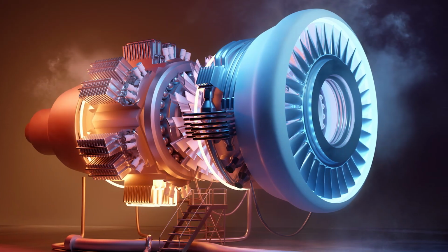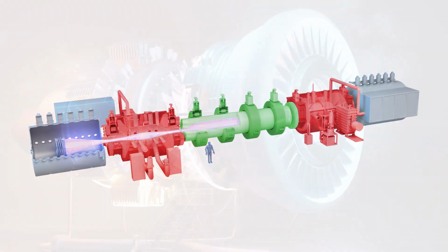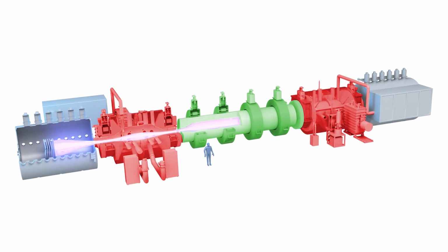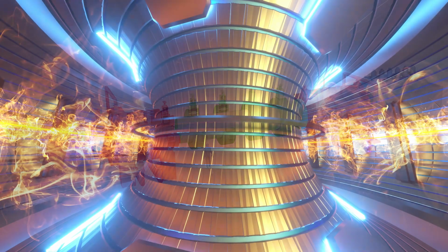We're looking at ways to make new alloys that are going to give us a boost in the energy economy. One way to do that is to go to higher operating temperatures. The jet engine will operate around 1100 degrees C. We're looking at going to 1300 degrees C, or for hypersonics, or for fusion energy, for first wall diverters or reactors. We're looking to increase the temperature because with increased temperatures we get increased efficiencies. Therefore, we use less fuel, and that's good.